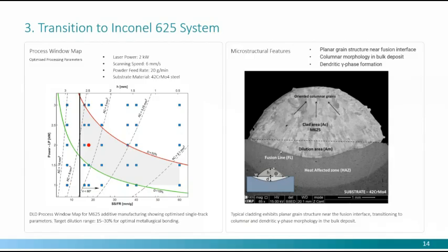Inconel is a much easier material, with very good properties in terms of direct energy deposition. What we found, after a lot of experiments again, is that we had a very big process window, so we can change the parameters. Laser power was one of the most interesting parameters, and then we see you have very nice deposition with very good microstructure. It looks very good, planar.